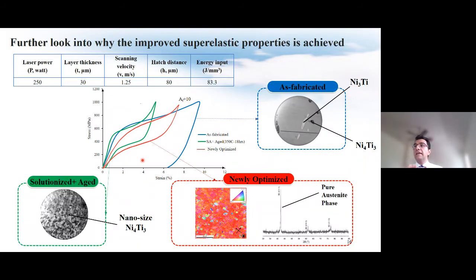On the other hand, the as-fabricated SLM NiTi samples in the literature demonstrate almost no superelasticity, and that is why the standard of care is to perform post-processing heat treatment on the as-fabricated samples to create a desirable level of superelasticity as well as enhance the strength of the material by inducing more Ni-rich precipitate. Anyway, post-process heat treatment should be avoided as it involves extra time, costs, as well as labor training, and some other associated costs. By the way, even with post-process heat treatment, the highest achieved superelasticity in the literature was only 4.3%, which is absolutely lower than that seen in our newly optimized specimen.